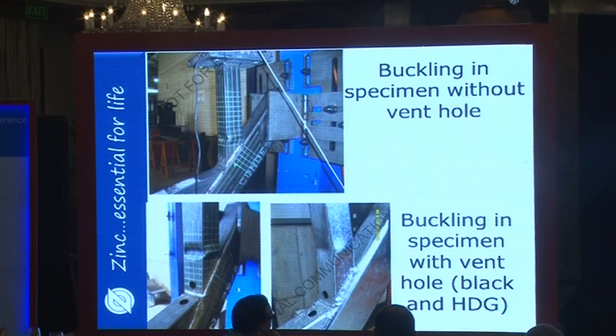As long as we put the vent holes down near the welds, the buckling will occur away from it. So this is good news for the designers who worry that if you put in vent holes, you're going to weaken the joints. And you actually don't weaken the joints at all because the failure occurs elsewhere.